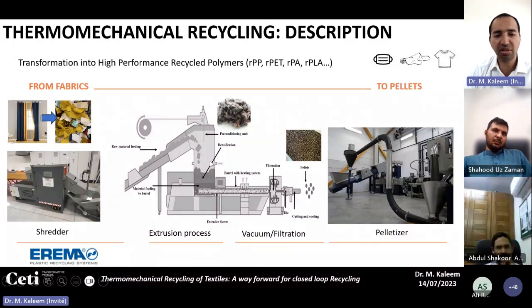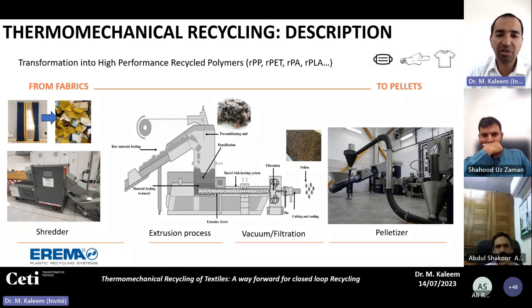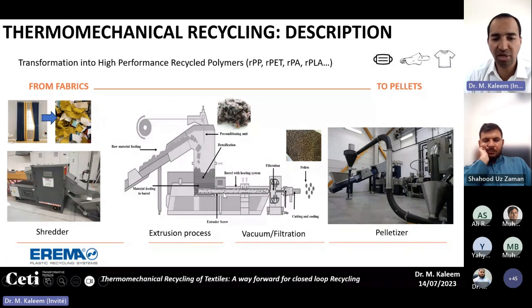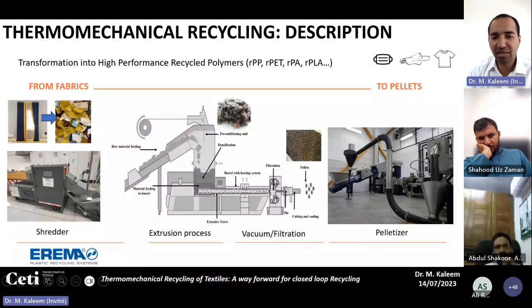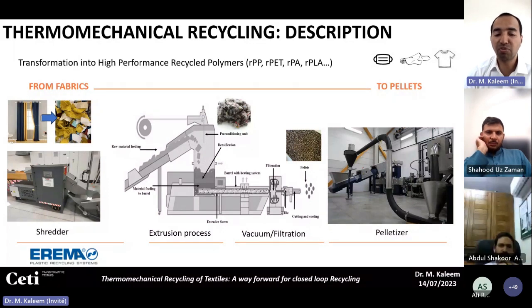After this densification step, the material goes into the extruder, like if you have experience with polymer extrusion. You feed that feedstock into the extruder, apply high temperature and pressure, and you get a polymer melt stream. Then you filter and remove all the contaminants, because post-consumer textile waste requires high filtration to remove all the impurities in the textile. If the filtration is not well done, it may cause processing problems during the fiber development afterwards. So the filtration must be very well done here.